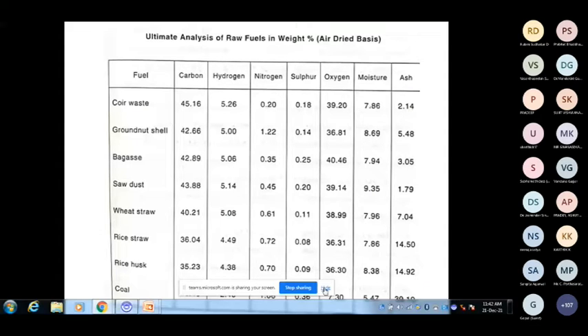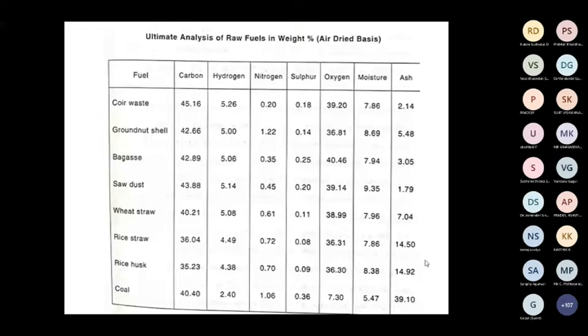So these are the typical results of ultimate analysis for the 7 biomass fuels. I compared with coal also. The bottommost is the coal. If you see the carbon content of the biomass, it is almost similar to coal. Here you have 45%, 42%, 42%, or straw fuels maybe around 35, 36. Almost similar to coal as far as carbon is concerned. But interestingly, if you see the hydrogen content, coal has 2.4% hydrogen, whereas all biomass fuels are more than 2 times that: 5.26%, 5%, 5%. So the hydrogen content of biomass fuel is more than 2 times that of coal. In that way, it's a better fuel.